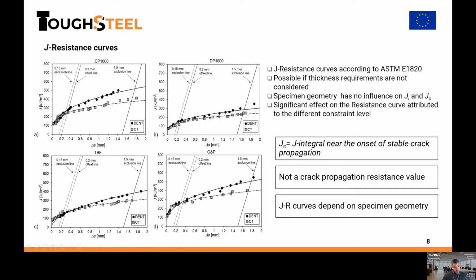This is the J integral again, near the onset of stable crack propagation, as determined by this offset line. It is important to keep in mind that this is not a crack propagation resistance value, but is rather related to the initiation, or by definition, is the J integral point near the onset of stable crack propagation. And also it's important to keep in mind that these resistance curves depend on specimen geometry, so this is not a property of the material.